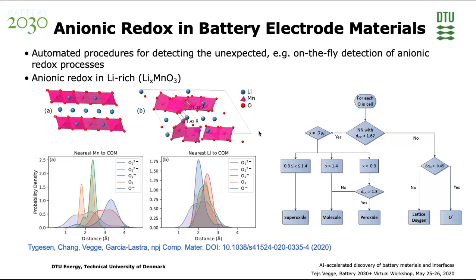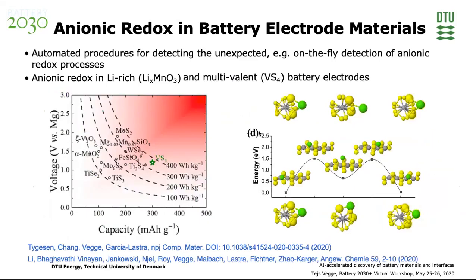And this is not something that's only interesting for lithium. Very nice work from HIU by Senyun Lee and collaborators also looked at multivalent electrode materials like VS4 and analyzing then that it is also anionic redox process taking place, combining it with simulations to assess the kinetic properties of the materials. So this is sort of the toolbox that we're dealing with on the simulational side to put into BigMap.